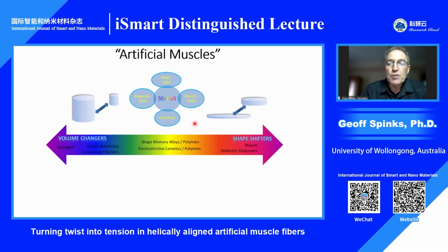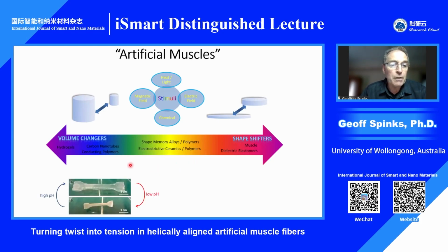And we can think of perhaps a spectrum of these materials, which are either volume changes or shape shifters, or some show both of these actions. The volume changes might be things like hydrogels, for example, highly swollen polymer networks. This photograph shows a pH-sensitive hydrogel, where at high pH it achieves a large volume, and then at low pH it shrinks down to a much smaller volume, and that process is reversible depending on the pH. That's just one example of a volume changing material.